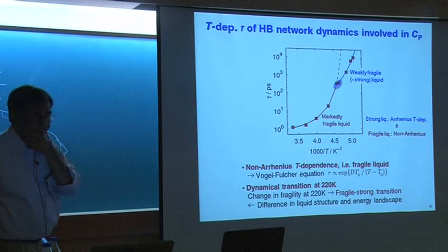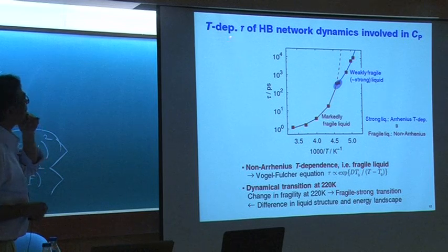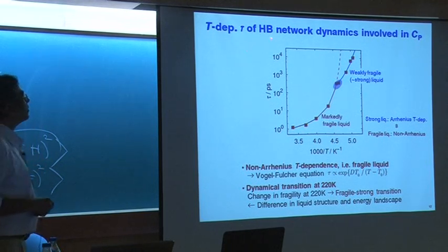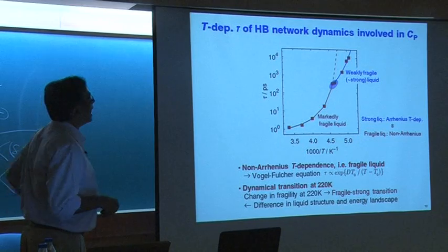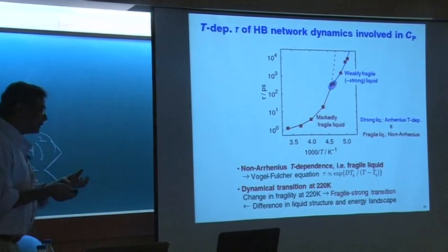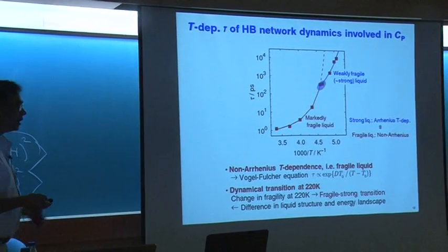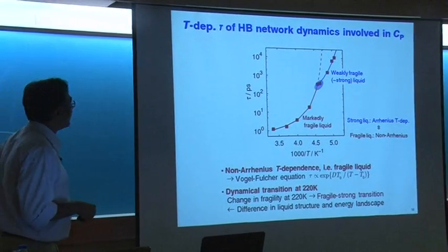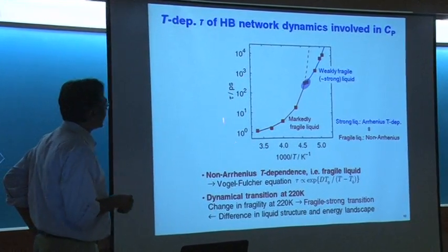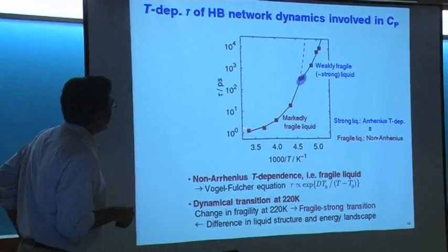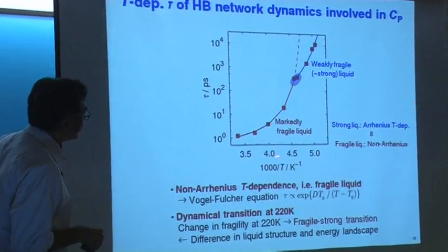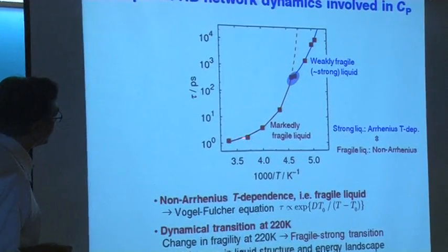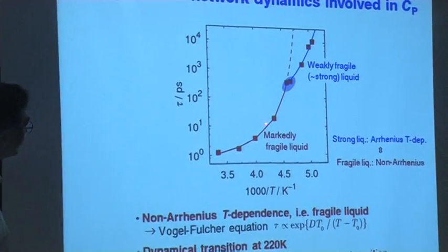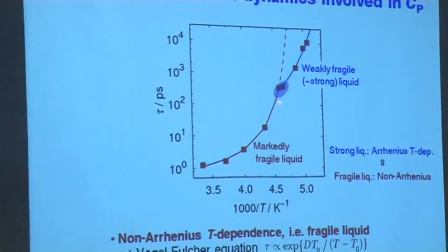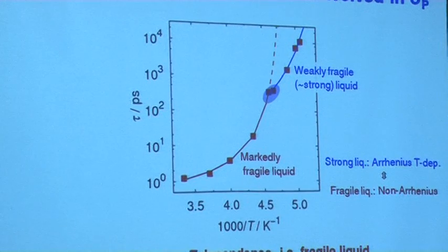Now, temperature dependence of the relaxation time of hydrogen bond network dynamics. Hydrogen bond network dynamics you find out by asking what is the lifetime of a hydrogen bond, and you find the time correlation function of that. So that is now in picoseconds, and what about temperature? This region is high temperature. At high temperature, it is growing almost like Arrhenius. Then it becomes what we call super Arrhenius, that is, stronger than Arrhenius.